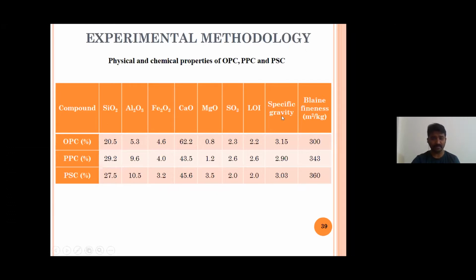These are the chemical properties. Remember, OPC has the highest specific gravity, PPC is slightly lesser than that, and PSC is very close to OPC. Even if you see the Blaine's fineness, OPC fineness is slightly lesser, PPC slightly higher, and PSC is the finest cement.